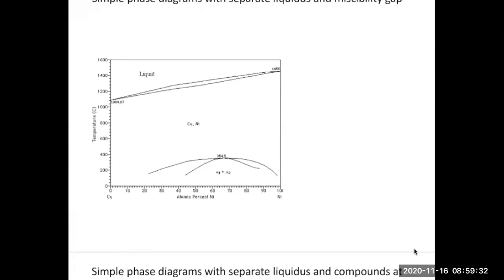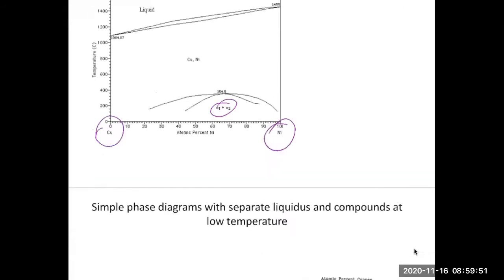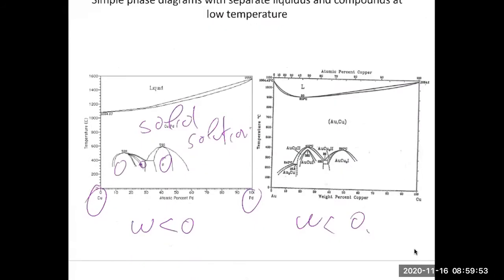And here you see another system, this is copper nickel. Again, usually categorized as a solid solution, but it actually has a low temperature miscibility gap. But if you look, the temperature of the miscibility gap is about 200-300 degrees. And so it's very hard to actually see it because your kinetics gets very poor. Here's some more. This is a lens in copper palladium, where again you have low temperature features and then a slightly deformed lens.